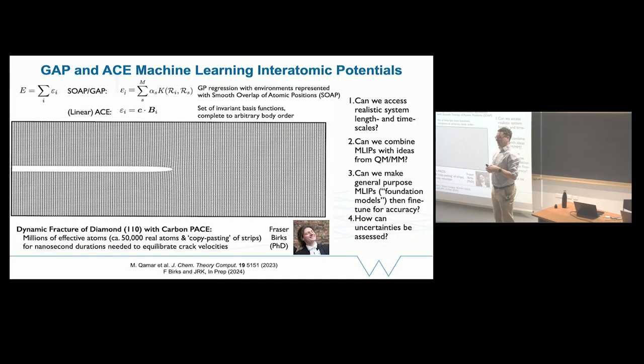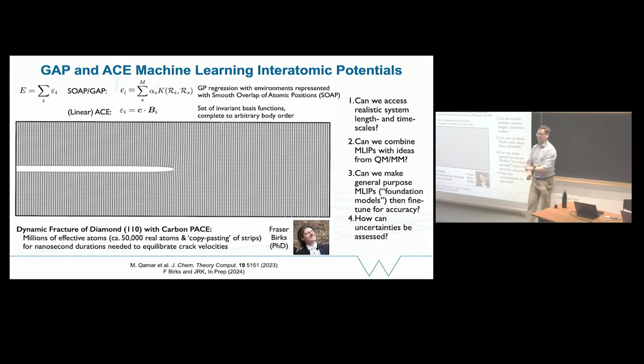If you're only interested in the onset of fracture, it's better to use a different geometry where you apply a displacement field that you get from continuum mechanics on the boundary. So the details depend on the problem, but yeah.